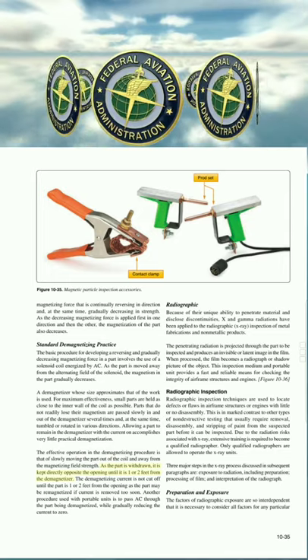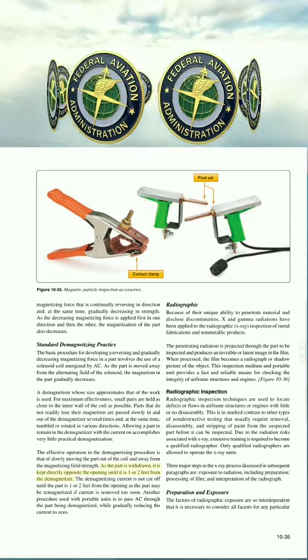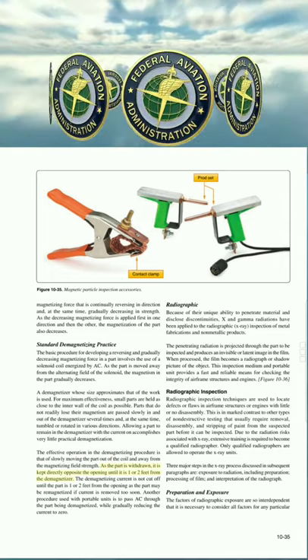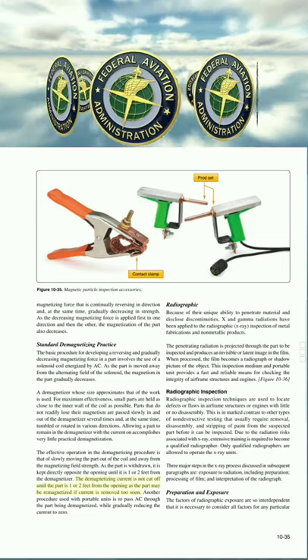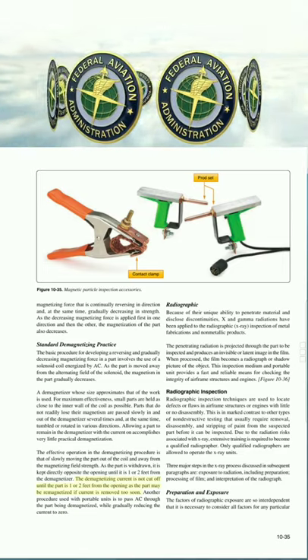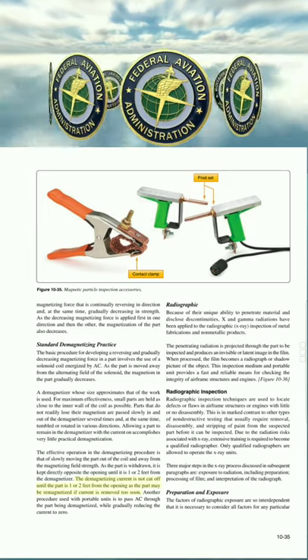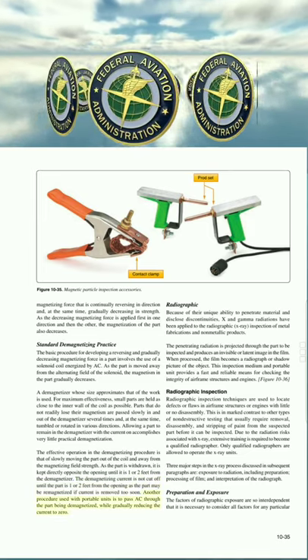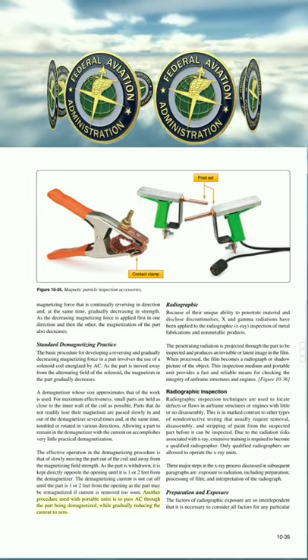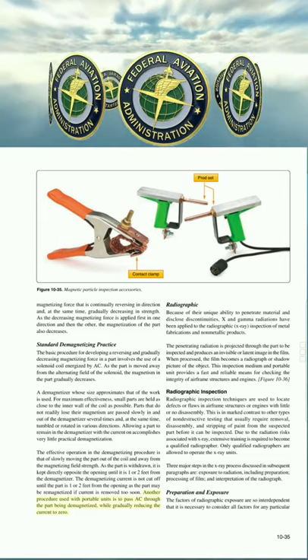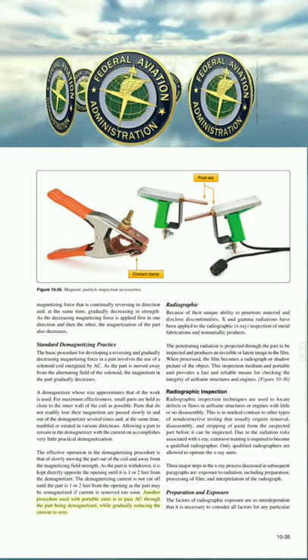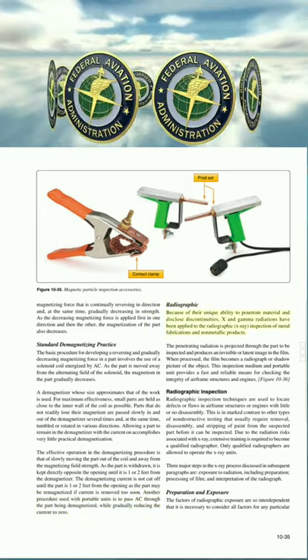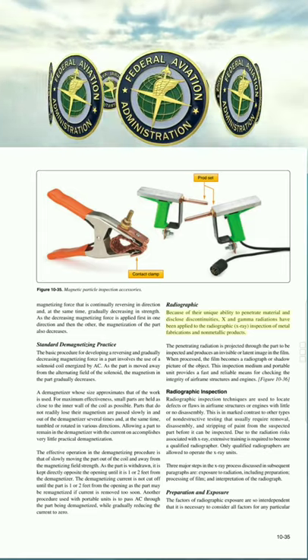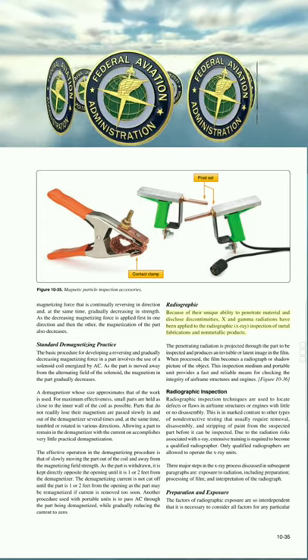As the part is withdrawn, it is kept directly opposite the opening until it is 1 or 2 feet from the demagnetizer. The demagnetizing current is not cut off until the part is 1 or 2 feet from the opening, as the part may be remagnetized if current is removed too soon. Another procedure used with portable units is to pass AC through the part being demagnetized, while gradually reducing the current to zero.